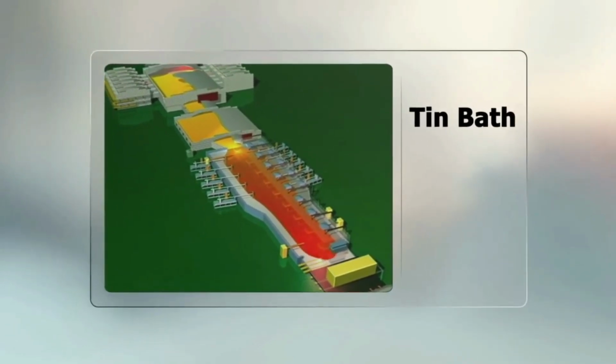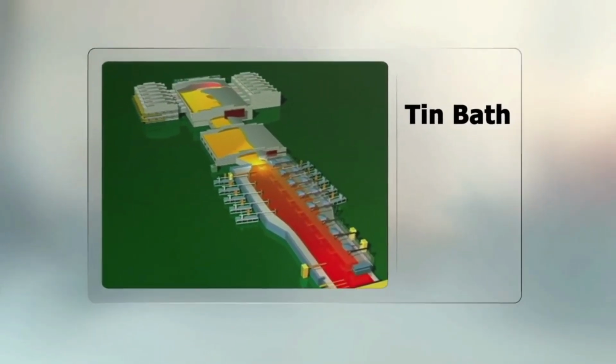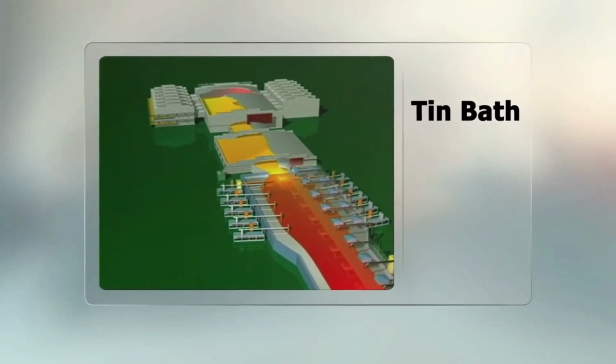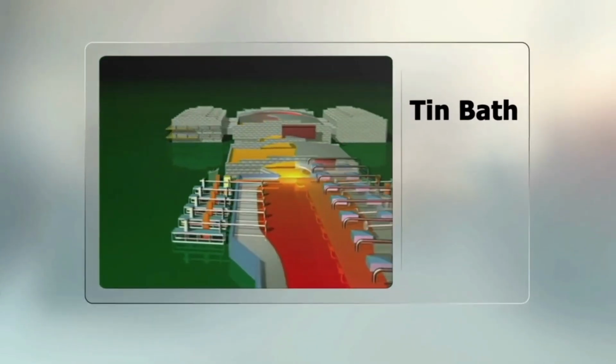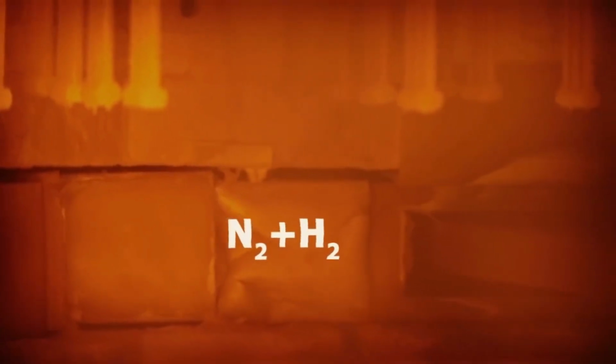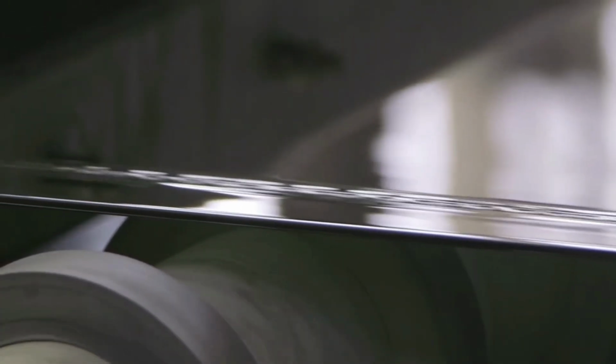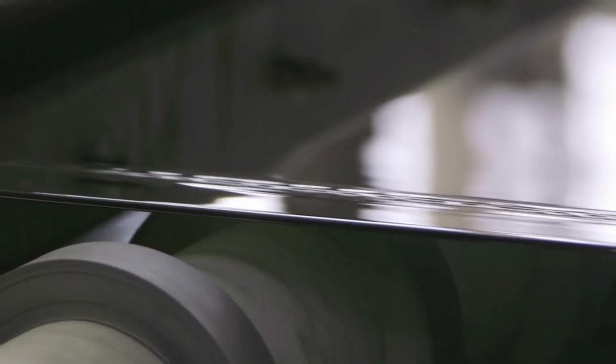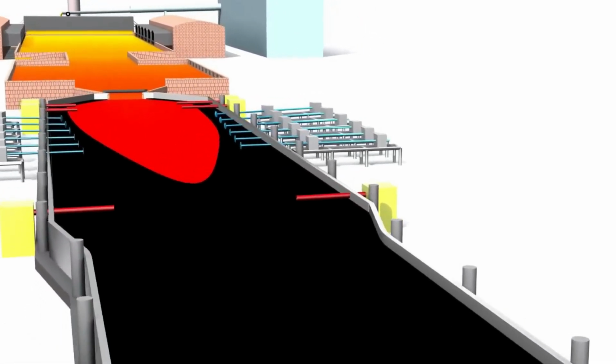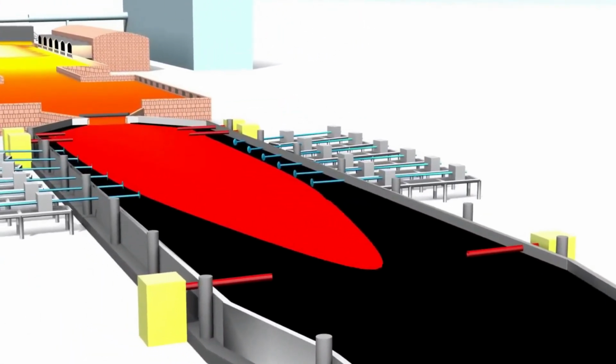As the molten glass is poured into the tin bath, it spreads and floats on the surface of the tin. This happens at a temperature of about 1000 degrees Celsius or 1832 degrees Fahrenheit, whereby the glass is still soft and pliable. The molten tin provides a perfectly smooth base, which allows the glass to flatten out because of gravity and surface tension alone. These forces combine to ensure that the sheet of glass produced is uniform with both sides smooth. Because the glass has a different density and the tin is non-reactive, it will not stick.